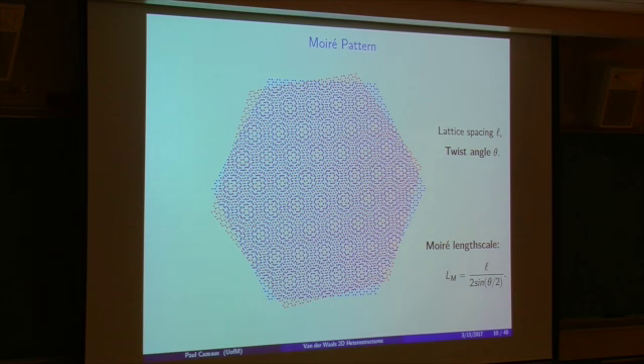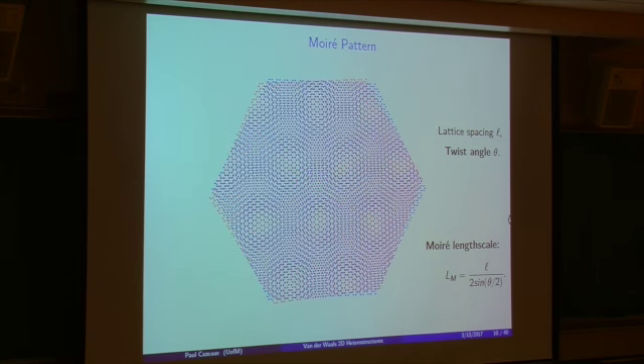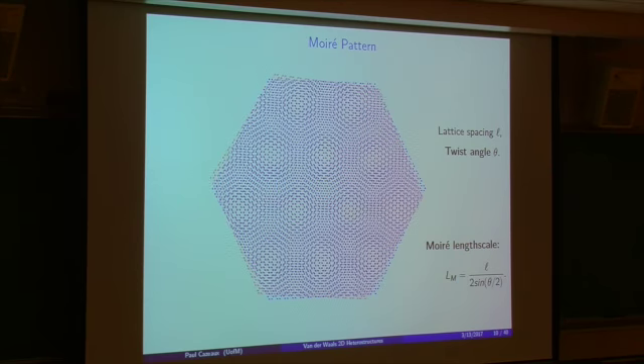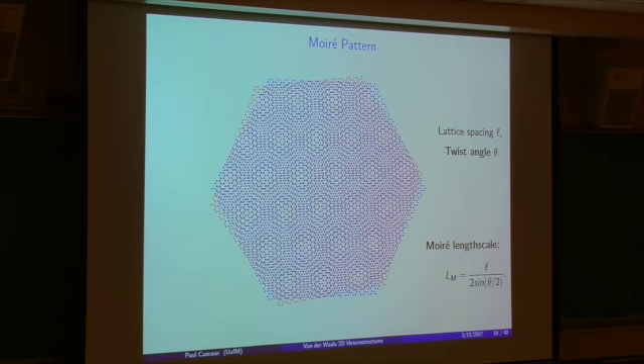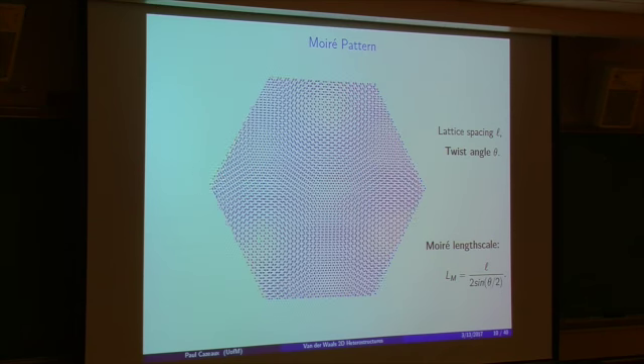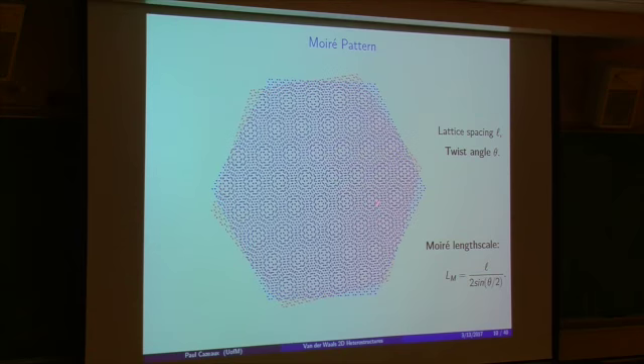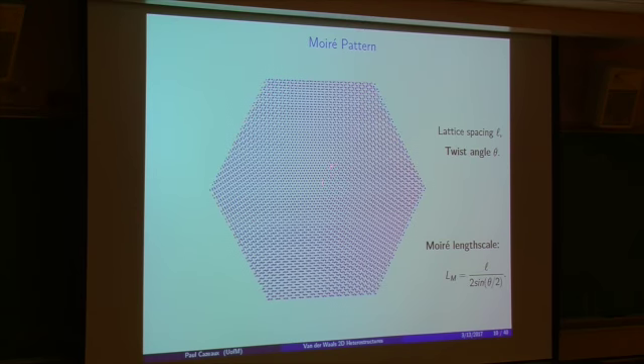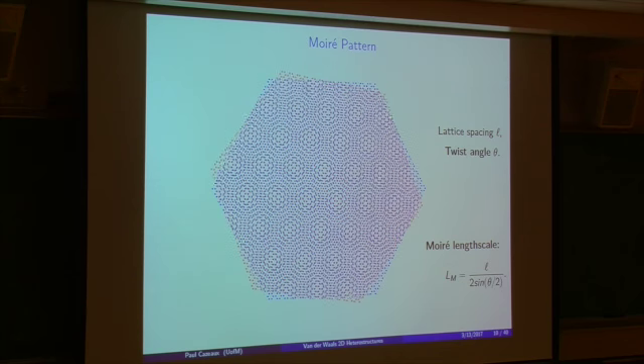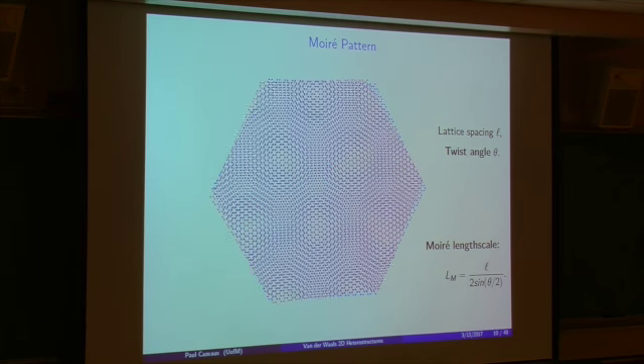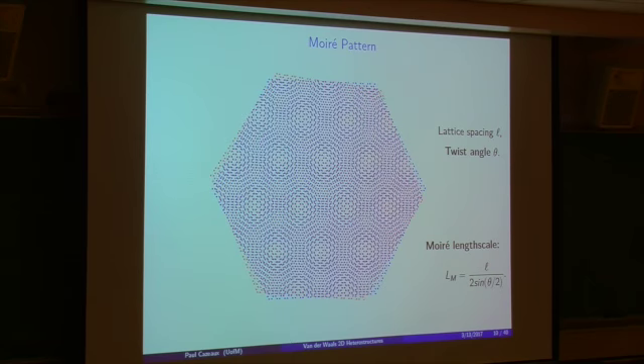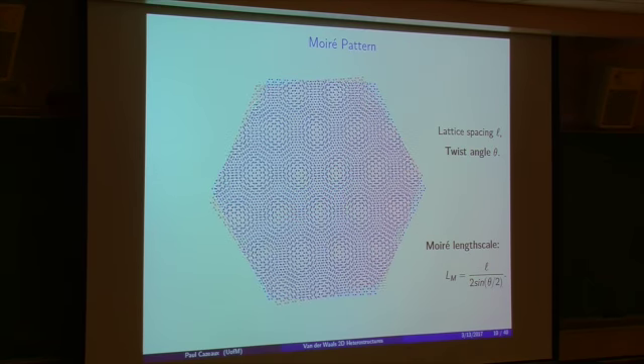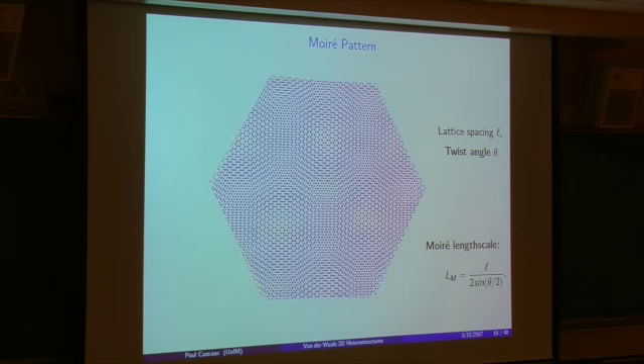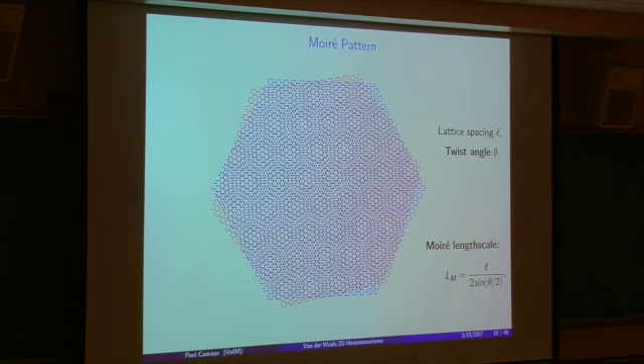So what is it? This is an explanation of what the Moiré pattern is, in terms of a small animation. If I have two lattices with the same lattice constant on top of each other, both hexagonal lattices, and we have a twist angle between the two, then we see with the naked eye a pattern appearing. We have these loops over here, and we see that the distance between them changes as the angle changes. This gives us a length scale, the Moiré length scale, which is not quite periodic but really quasi-periodic, and which depends on the angle; especially at small angles, it's inversely proportional to the angle.